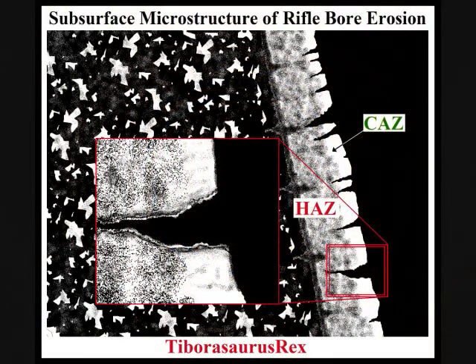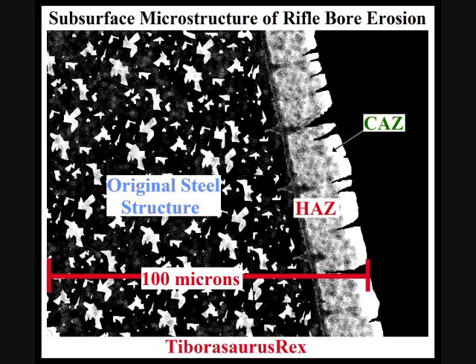And another thing that occurs, and I did hint at it, is thermal shock. That's basically a sudden, extremely steep temperature gradient from the bore to the cool part of the barrel, and that's what results in your cracking, especially in the chemically active zone where the steel's already kind of brittle. So you're going to have micro cracking. And also, you can sometimes see this a little more easily. You're going to have heat checking, and that's that alligator skin-like appearance. I don't know if you guys have seen pictures of heat checking. Some of the reloading manuals talk about that, but that's that alligator skin-like appearance forming from all the different cracks in the bore due to the erosion. So that's something you want to keep in mind.